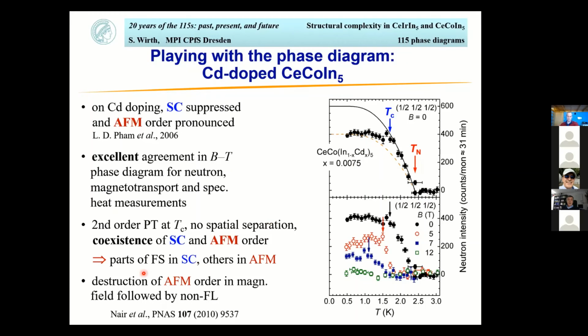And basically, since we don't have any indication for any spatial separation in this material here, this is a second order phase transition at TC, so we think there is a coexistence of superconductivity and antiferromagnetic order. So some parts of the Fermi surface seem to be in the superconducting states, other parts in antiferromagnetically ordered states. I should also note that contrary to this general phase diagram I have shown, even by applying high magnetic fields of 15 Tesla, we don't get into a Fermi liquid regime. We always stay in non-Fermi liquid regime. But this is just a side remark.